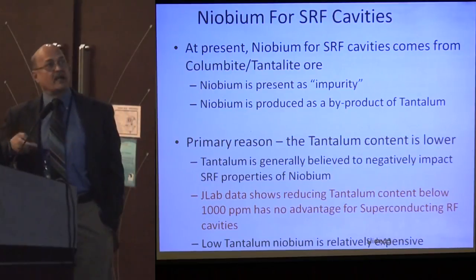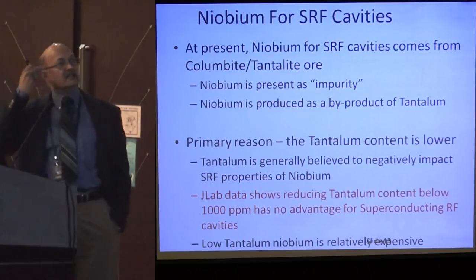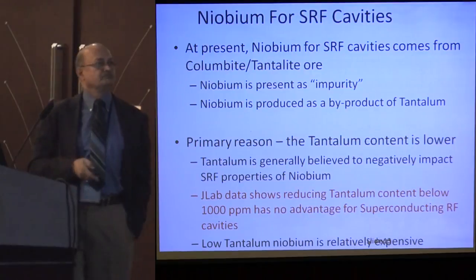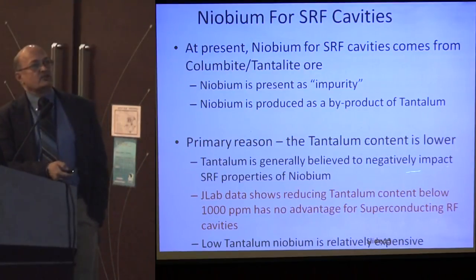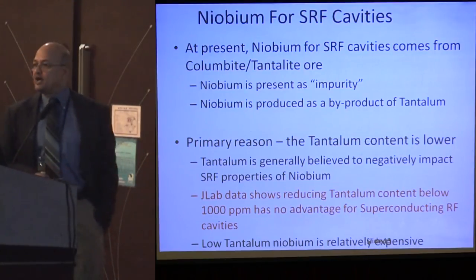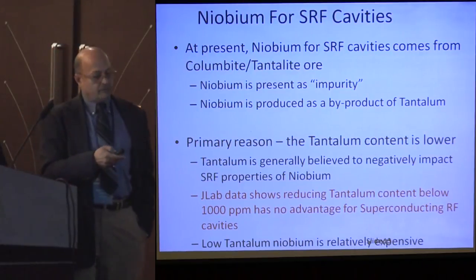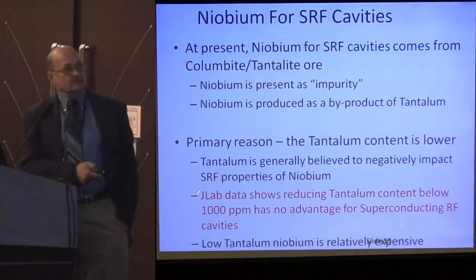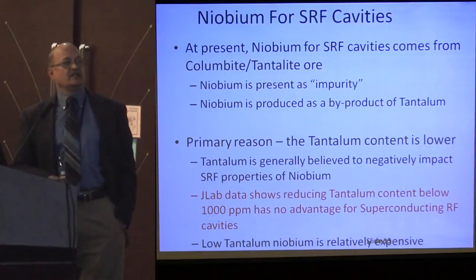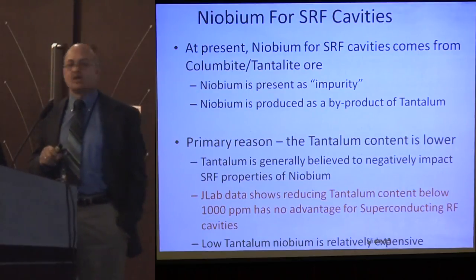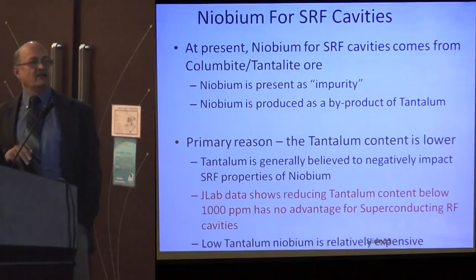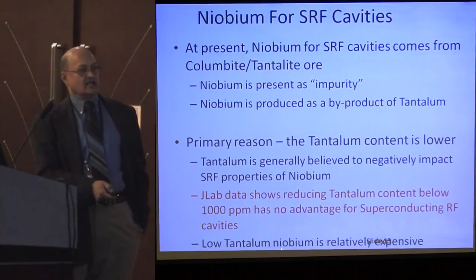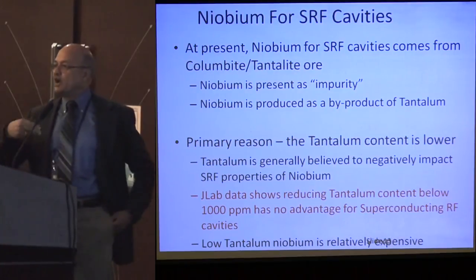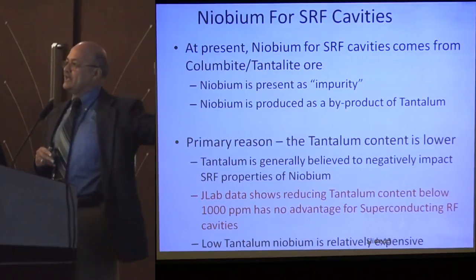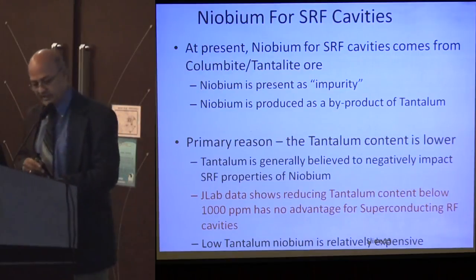And the current specification for the tantalum content is less than 500 weight ppm. It is generally believed to negatively impact the SRF properties of niobium. But the data from Jefferson Lab shows that reducing tantalum content below 1,000 ppm has no advantage for the superconducting RF cavities, whereas the low-tantalum niobium is relatively expensive. So if you want to cut down the cost of these things, one has to relax the spec. That's all I'm trying to say here.